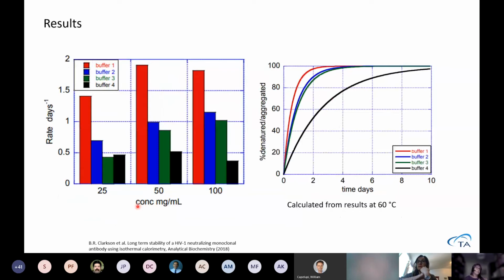So again, data could be fitted with this nonlinear least-squares fitting, and we can get the reaction rates by building these models of unfolding and aggregation. We can see different buffers depending on concentration. The higher the concentration, the faster the denaturation goes, or the aggregation in this case. And they could then rank the buffers correspondingly by the reaction rate.